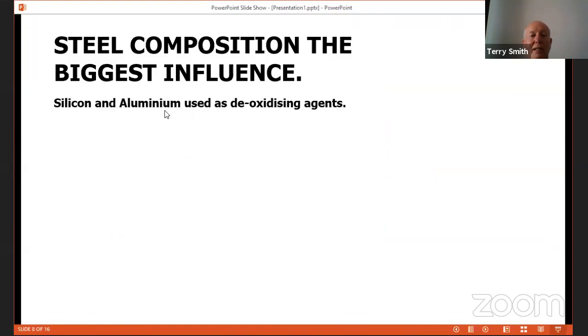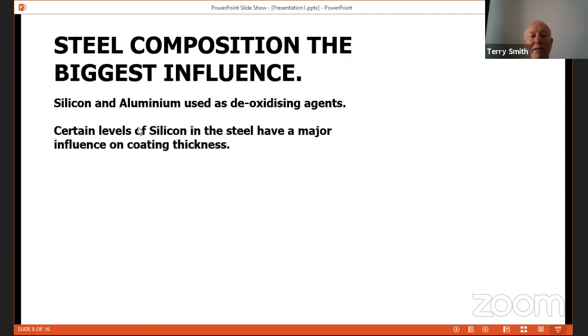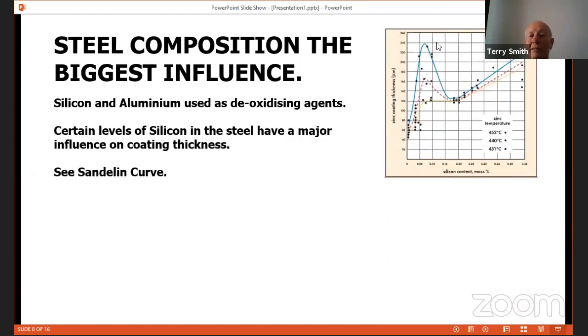Silicon and aluminium are used as deoxidizing agents. As you're making steel, the molten steel has to be deoxidized, otherwise it will create slivers and laminations in the steel. So they use silicon and aluminium. Aluminium doesn't really have a problem, but silicon in various levels can create major influence on coating thickness. Here we have the Sandelin curve, and to the right here you can see this is the Sandelin curve. On the y-axis is increasing coating thickness. On the x-axis is between 0 and 0.5% silicon.